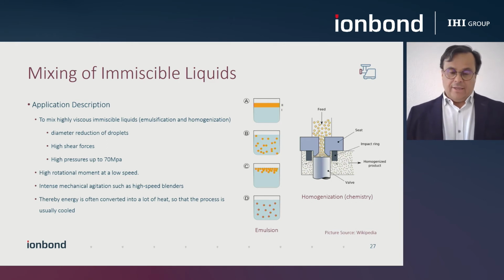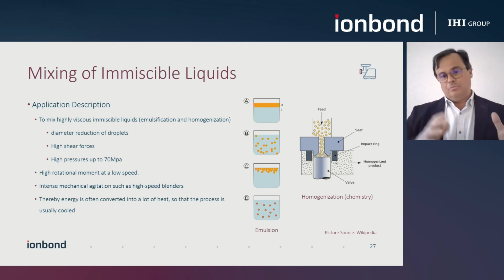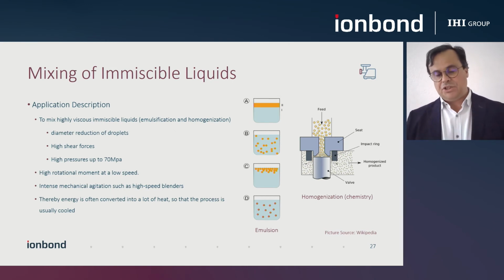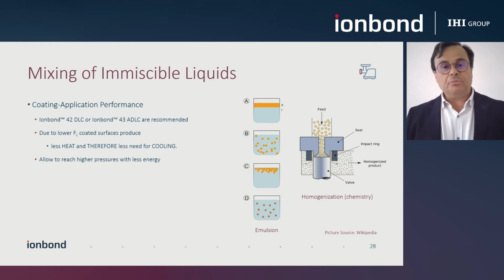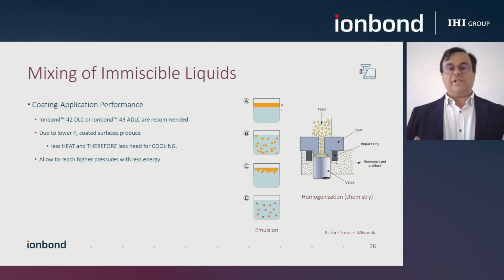When we look at the drawing, with the scale having a slight difference, it is a very similar application compared to the injection pumps in the automobile industry, where we also successfully apply coatings like diamond-like carbon coating on these devices in the cars that we drive every day. So this shows the technology is safe, and this explains why, for this particular application, we recommend the use of diamond-like carbon coatings, because they have this low friction coefficient. They allow you to produce less heat, so you can cool less, but also increase the pressures in the applications and consume less energy.